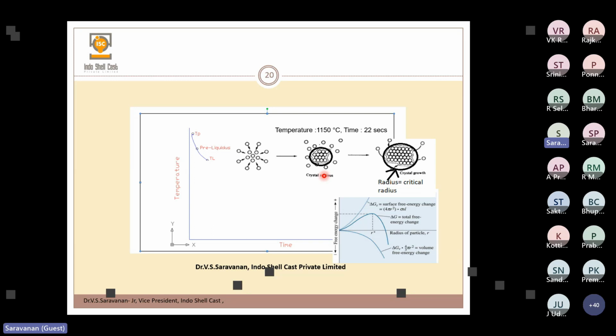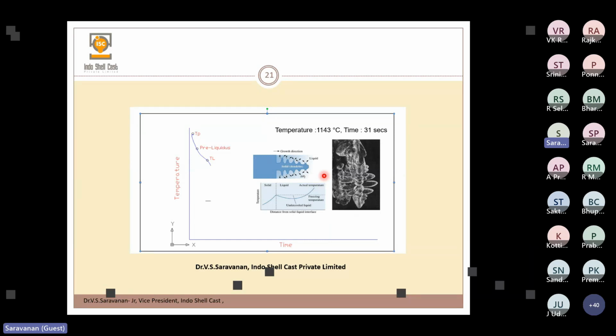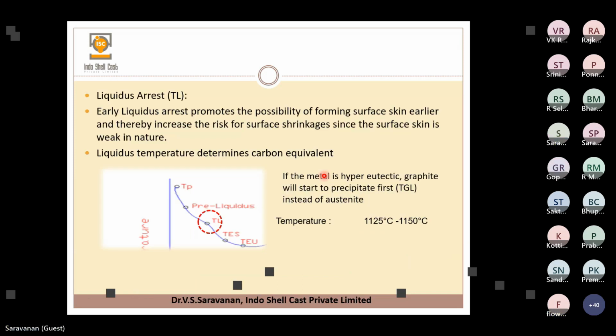What happens here is that the first nucleation sites form and then start growing slowly. There are two types: hypereutectic and hypoeutectic. Hypereutectic means the first solid may be graphite. Hypo means the first solid may be austenite. So austenite tends to precipitate and then slowly grow. This is TL, the liquidus point, and then it grows slowly. The dendrites go in all 360 degree directions as they grow. The early liquidus arrest promotes the possibility of forming surface shrinkage, because early liquidus arrest means a larger amount of austenite will form, so there are chances of getting surface shrinkage defects. How to bring these down, we will see later.